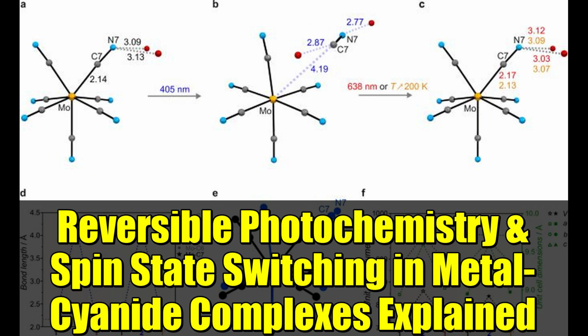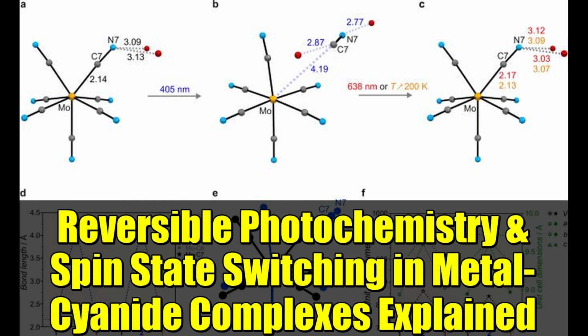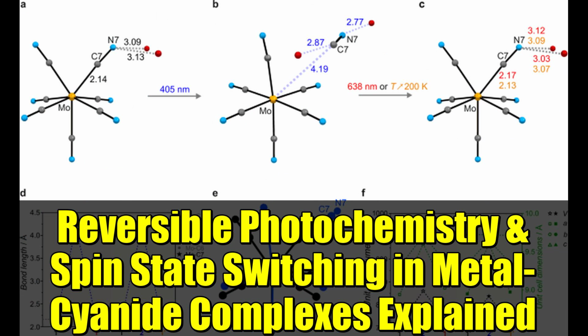Notably, the relaxation temperature of 150 K for 2 surpasses that of previously reported spin crossover systems, suggesting an unusually long lifetime of the photo-induced state in this molybdenum-cyanide complex. To quantify the characteristic time of the thermally induced 2-to-1 relaxation, time-dependent magnetization studies were performed at several temperatures in the 132.5 to 147.5 K range. The temperature dependence of the estimated relaxation time followed an Arrhenius behavior with an activation energy of